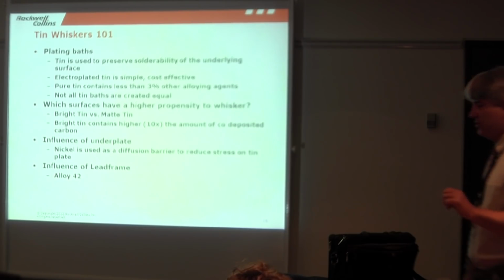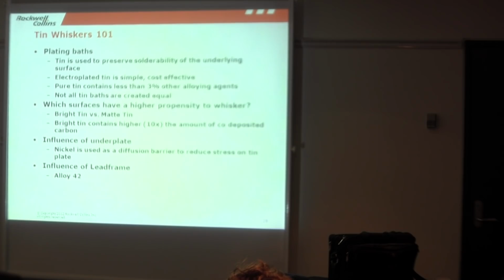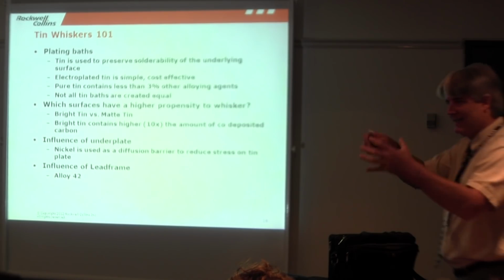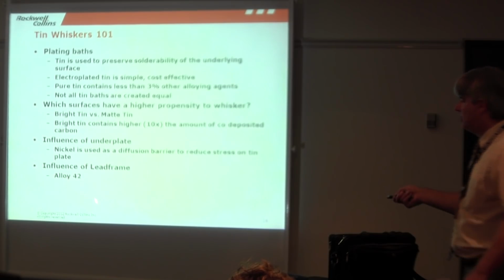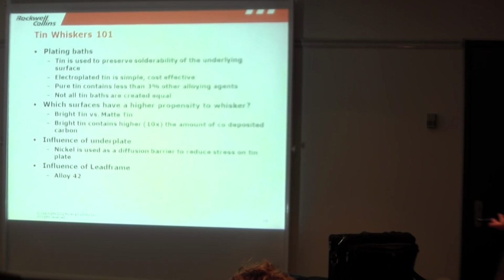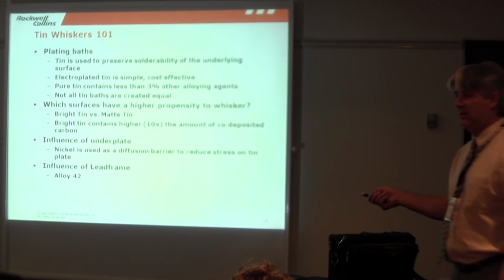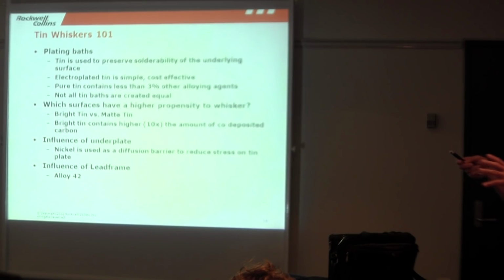Alloy 42 was used, it's gone away, thank goodness, in a lot of packages because it has a CTE of about 6 or 7, and a lot of the die and lead frames and glass around where the alloy 42 is used has a CTE of about 6 or 7. So it means it's matched and makes a really nice component. The problem is, at least what my mentors have taught me, if the stress isn't coming, so I don't have a stressed lead, but that stress has to go somewhere. It just doesn't go to 0. So where does it go? It goes into the finish.